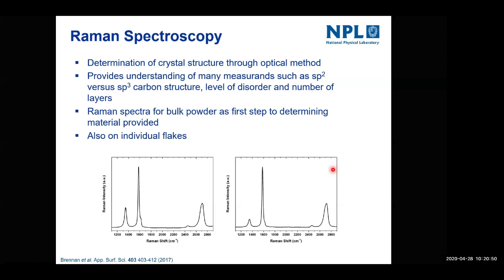Also, you have to be very careful distinguishing between measurement of a bulk powder, meaning the surface of that bulk powder, versus measurement of individual flakes. Going back to the flowchart we just saw, in the first instance you're just looking at the powder to see if it is graphitic. But later on, you can look at isolated flakes if you need to understand the number of layers specifically. It's a really big difference between those two that you have to be really careful about. And I'll talk a bit more about quality control at the end of Raman spectroscopy.